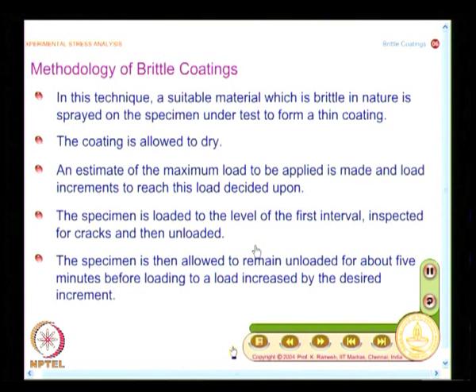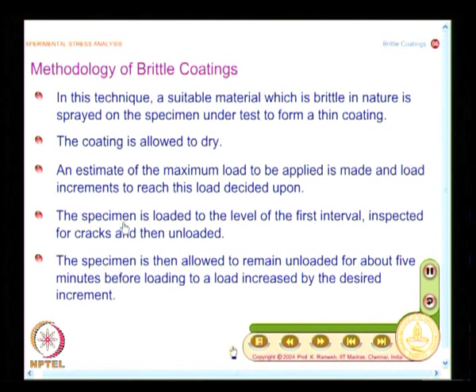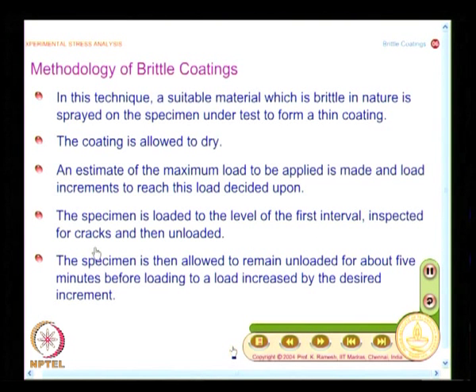The experimental approach is peculiar: estimate the maximum load, determine the load increment, and incrementally load after the first interval, looking for cracks. The crack pattern progresses with increasing loads, and the locus of points of crack tips is marked with a grease pencil. In a cantilever beam subjected to end load, the color used for each load increment also marks the ends of the cracks. These crack patterns are called stress trajectories or isostatics.